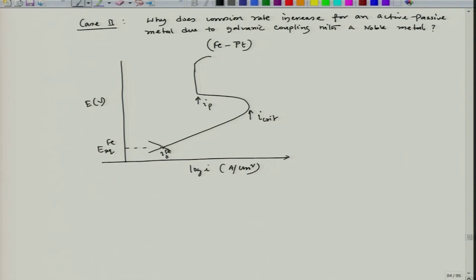Now, if we consider hydrogen evolution reaction, since this alloy is exposed to the acid, hydrogen evolution reaction becomes our cathodic reaction. Let us say the E equilibrium lies here, and it will have its own cathodic polarization. So let us say this becomes my I corrosion of iron when it is not galvanically coupled with a noble metal.